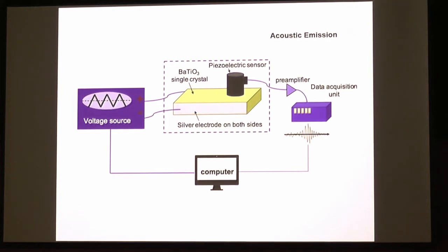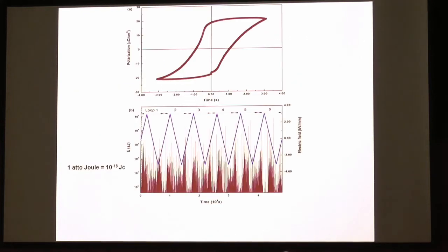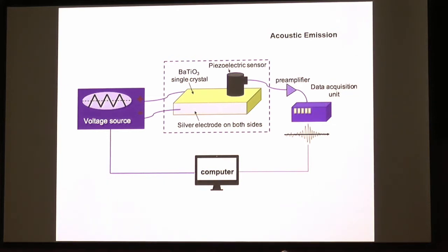And when we look at them only at the dynamics, then we can make an experiment where we use a barium titanate single crystal. We have electrodes on both sides here, and we put an electric field on. If domain boundaries move, they take the strain with them. This strain then leads to jerks, and these jerks can be measured by the piezoelectric sensor.